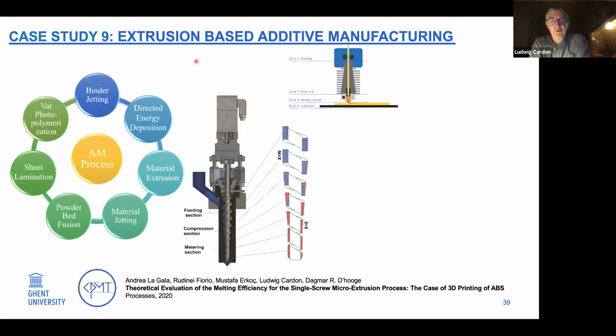What we investigate in our research group is a combination of, on one side, the standard filament extrusion, but also we developed a patented pellet extrusion micro extruder. It is very important to keep in mind that we have the pellet feeding system here, but in the first phase the material is not molten. In our design, we investigate the melting behavior depending on time and speed of the polymer, trying to find out the blending of the material, but also whether the pressurization is optimal and the temperature for afterwards deposition is optimal. In our patent, we have the possibility to control on one side the shear, so the heat, and on the other side the pressure distribution. It was also recently published in a journal.